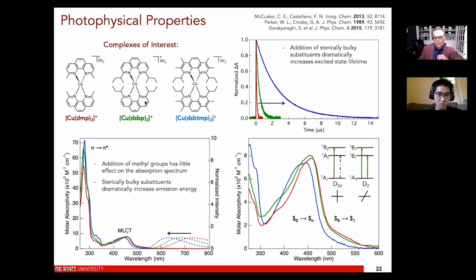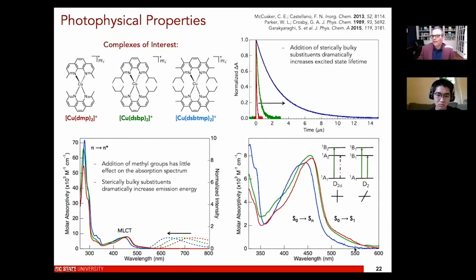This is a little bit better, but what I want to show you is that without having the flanking methyl groups, you see that the absorption band still kind of tails. So there is still a reasonable degree of distortion here. And then that manifests itself in it's still distorted a little bit, and then it's able to distort even further in the excited state, which leads again to a redder emission. But if you put the methyl groups here, you see what happens? This all kind of blue shifts, and you largely eliminate that low energy band. So it's telling you you're more in the D2d geometry in the ground state.